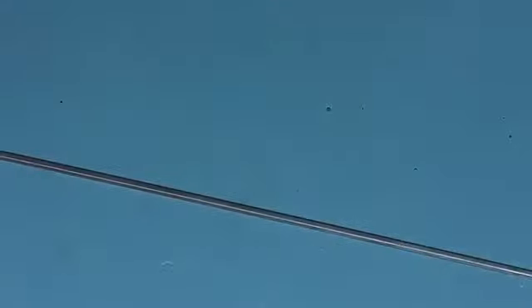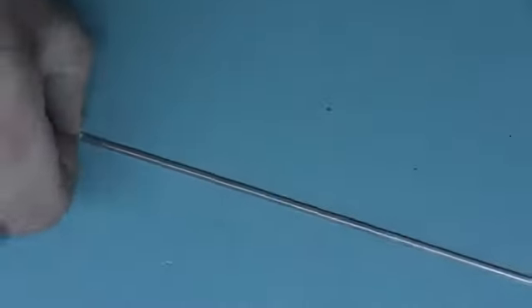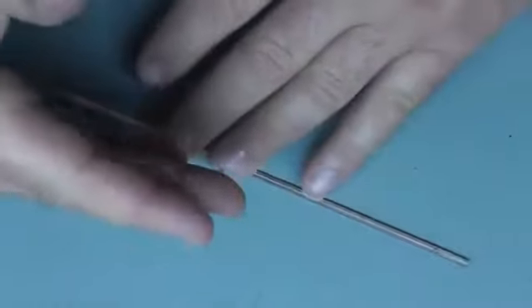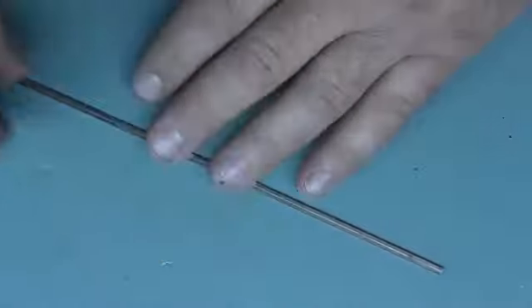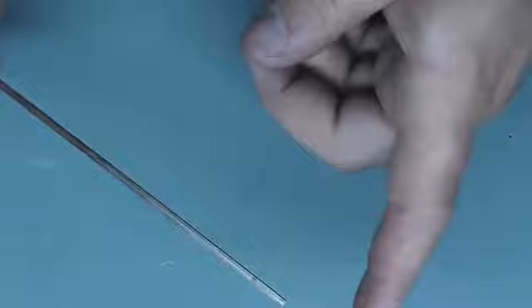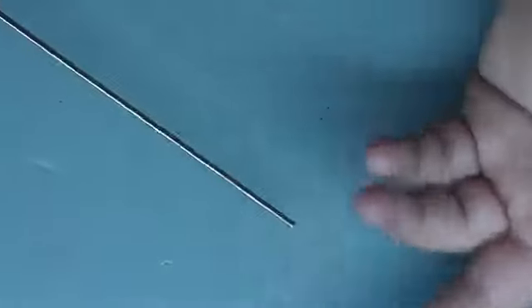But if you actually look up the specs on it, you can see that this is about 6% silver, and the other one, like I said, is 15% silver. But the melting points are pretty much the same, and tensile strength and everything else is pretty much the same. For this, it starts to melt at 1190 degrees, and it becomes completely liquid at 1470 degrees. So it starts to melt at 1200 degrees and turns completely liquid at 1500 degrees.